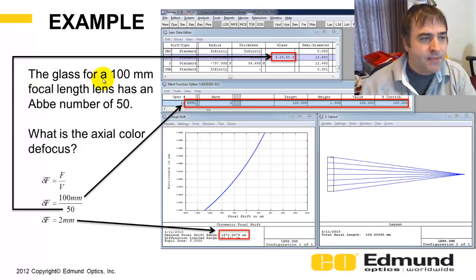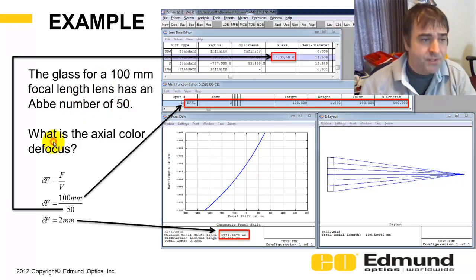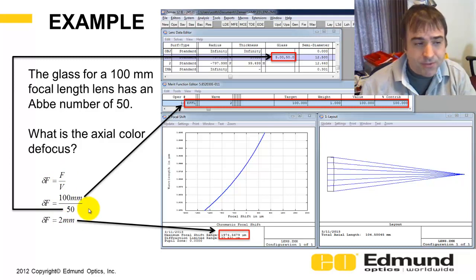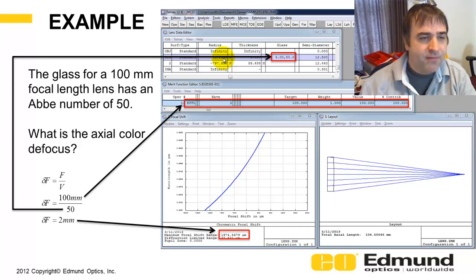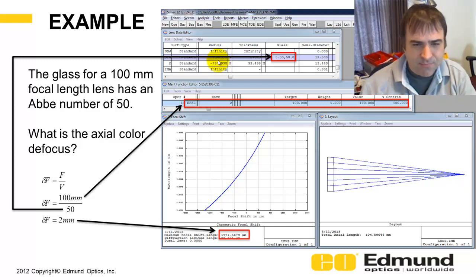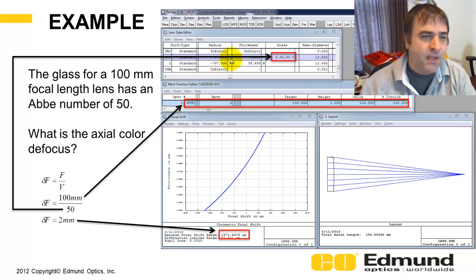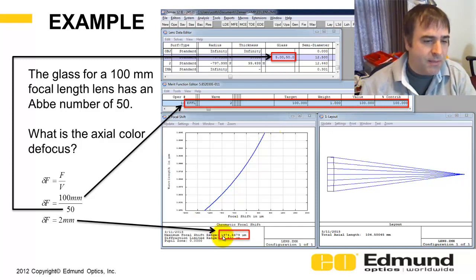Here's a quick example. Suppose we have a glass made into a 100 mm focal length with an Abbe number of 50. The axial color defocus, delta f, is simply f divided by the Abbe number — 100 divided by 50 equals 2 mm. To verify this, I modeled it in Zemax using a glass with index of 1.5 and Abbe number of 50, a bi-convex lens constrained to a 100 mm focal length. The chromatic focal shift result is 1974 microns, approximately 2 mm — confirming the theory.